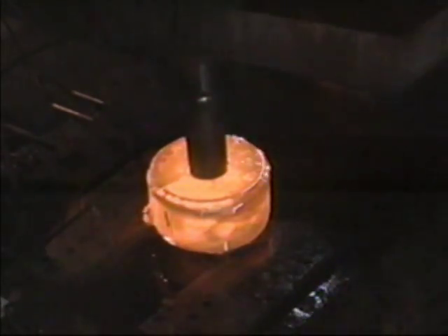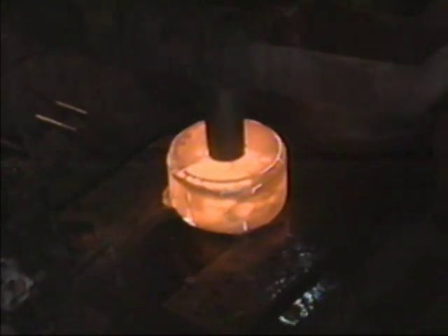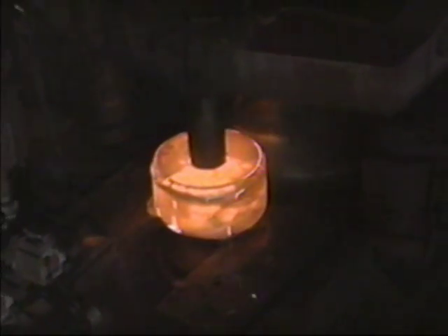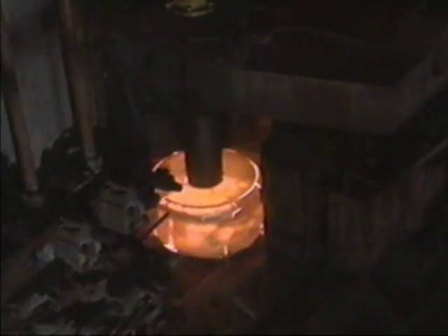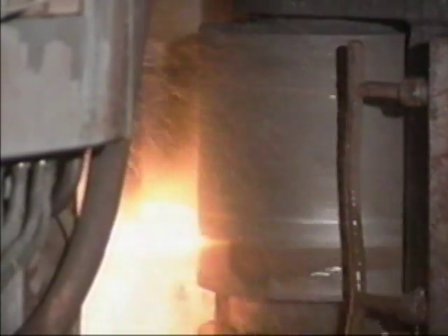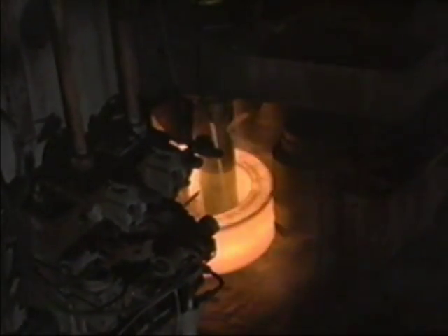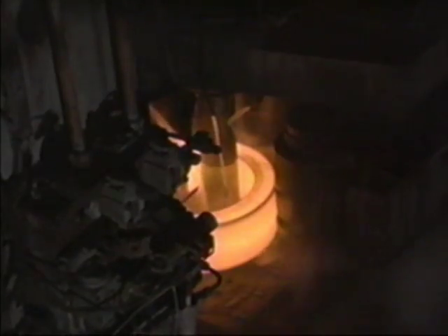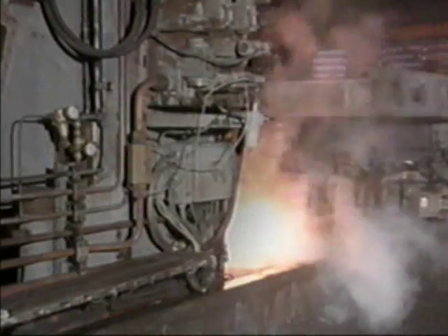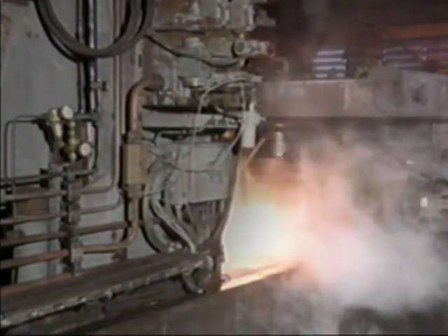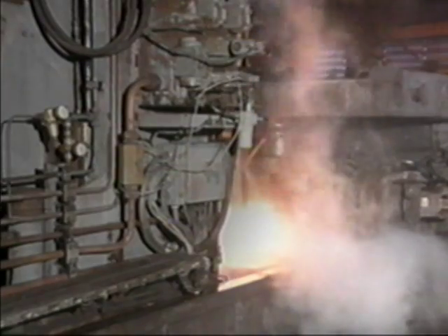Here a mandrel is inserted into the blank. The mandrel brings the hot blank against a large motor-driven main roll. When contact is made, the blank begins to rotate. Smaller centering rolls hold the blank in place. The mandrel continues to apply pressure toward the main roll, reducing the wall of the blank in the process. Tapered axial rolls above and below the blank reduce its height. As the wall thickness and height are reduced, the diameter of the hot ring grows.